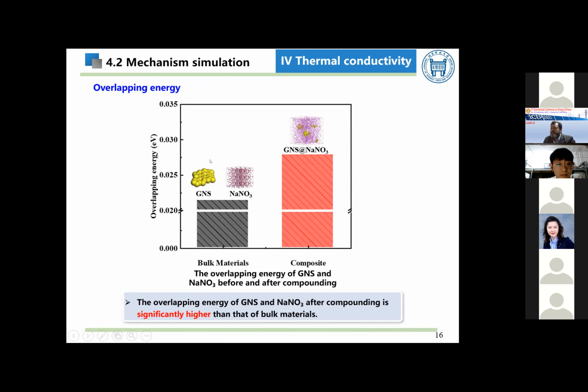The larger the overlapping energy, the more harmonious the vibration between the two materials. You can see the overlapping energy of GNS and sodium nitrate is significantly higher after compounding. So we can see that the improvement of the thermal conductivity of the composite material seems to be attributed to the vibration matching of GNS and sodium nitrate.